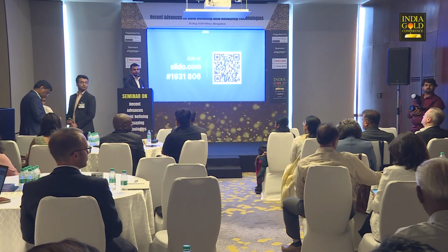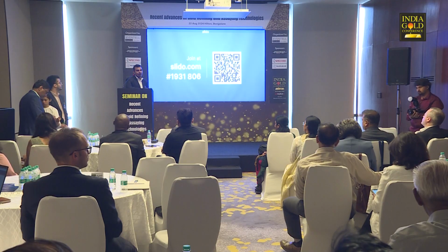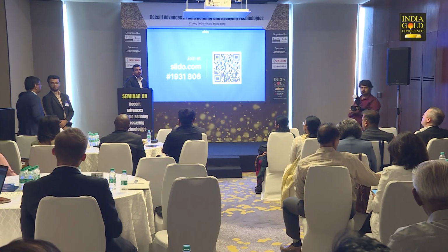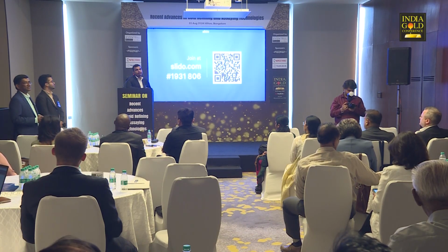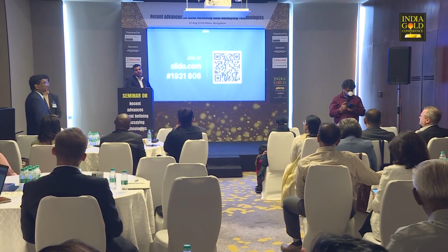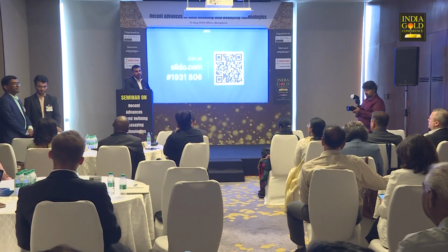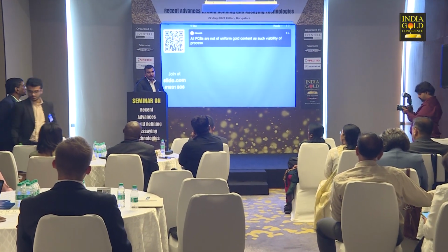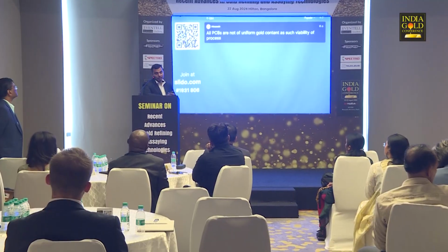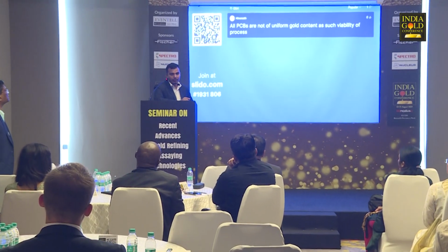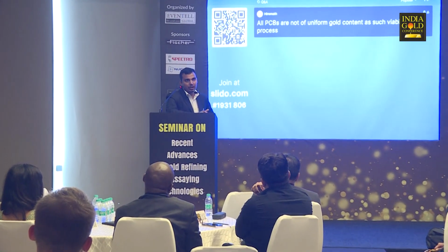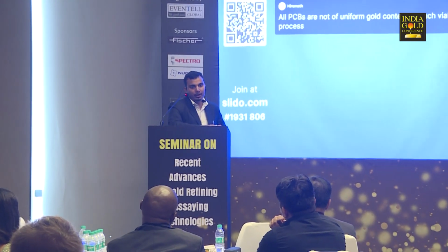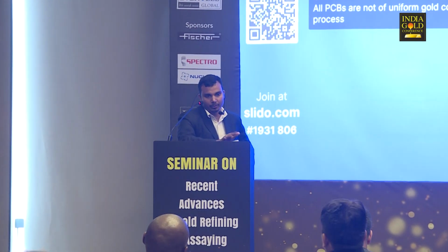What is the flux that you use in this, and the composition of the flux? It is typically what we have in the slag in this kind of pyrometallurgy process. So it is calcium oxide, alumina, not alumina actually, because alumina is already quite high in the fiberglass. Calcium oxide, silica, FeO, and a little bit of boric acid, or sorry, boron oxide.